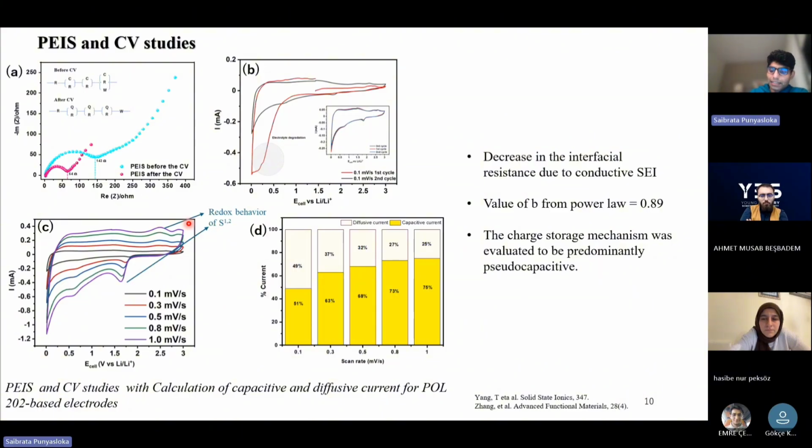Everybody has a way to do studies, and they decide how to read their data and what the next experiment is. For me, to understand any material properties, I first do an impedance study. It has its own flaws: very ideally speaking, the impedance study should be done with a reference electrode, and the counter electrode should not be polarizable. Once you keep getting experience, you develop these kinds of thoughts. But this is with lithium as the counter and the reference electrode, and it gives you a general understanding of how the material behaves.